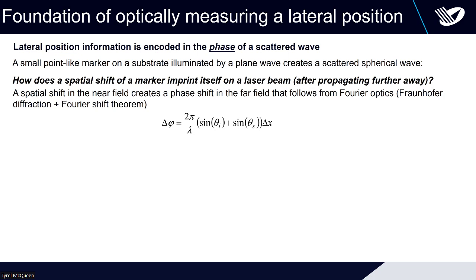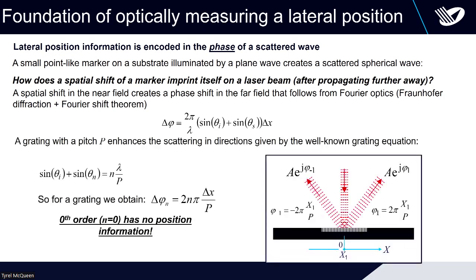So that is the phase shift you're getting from given wavelengths, an incidence angle theta I, and the angle of the outgoing scattered wave theta S. Then if you replace the scatterer with a grating, we get an enhancement of the scattering in the well-known directions that we get from the grating equation. So that corresponds to the different diffraction orders of the grating. We can plug in the grating equation for the relation with the angles. And then what we get is that the phase shift directly relates to a position shift of the grating divided by the pitch. And of course, the pitch you know, because that's what's being printed into the alignment marker.